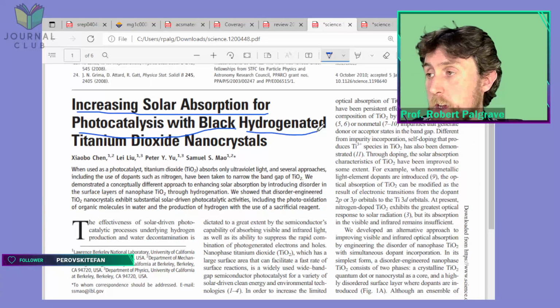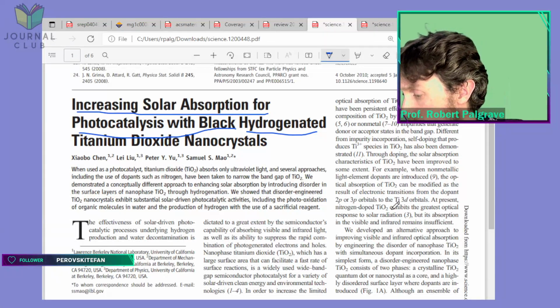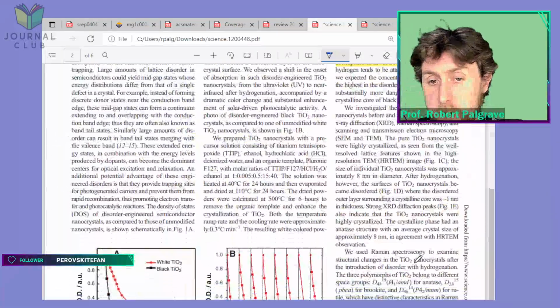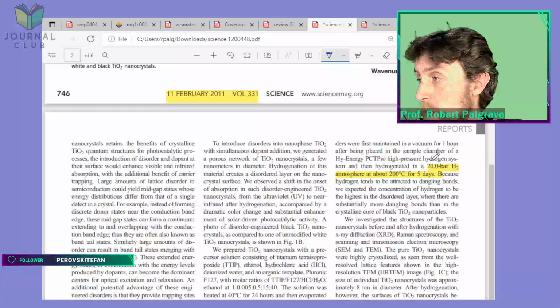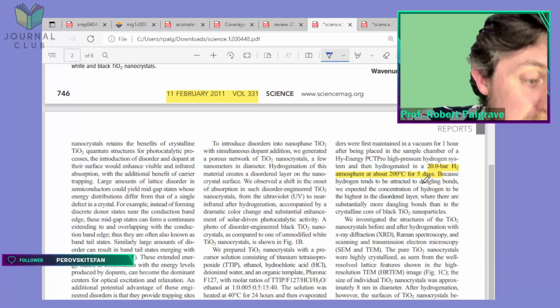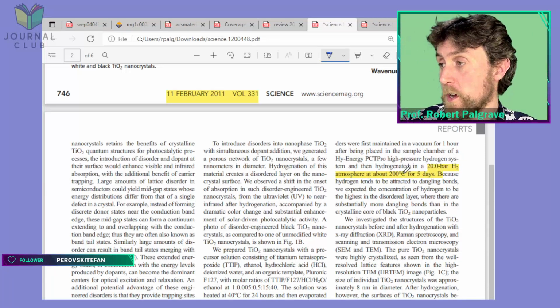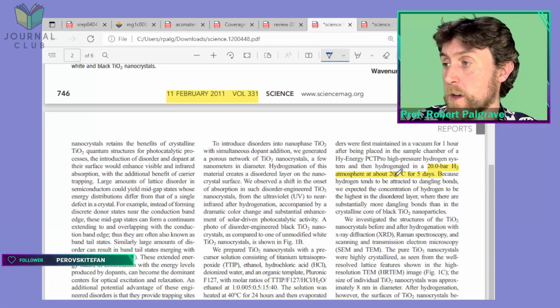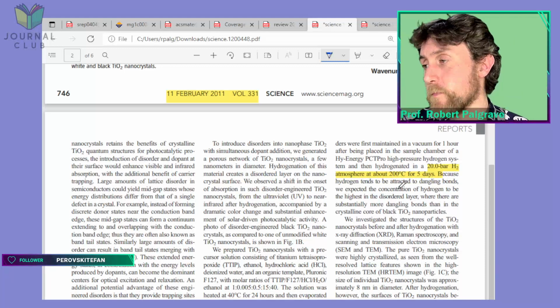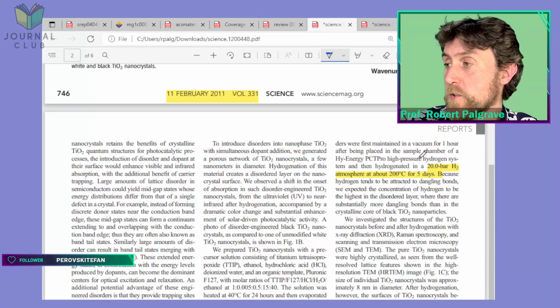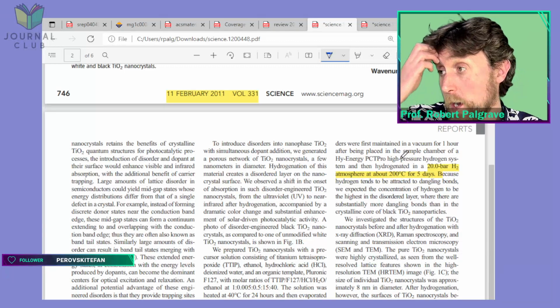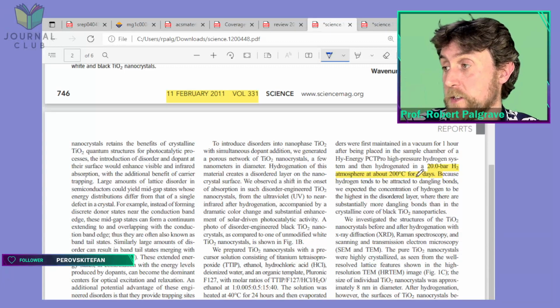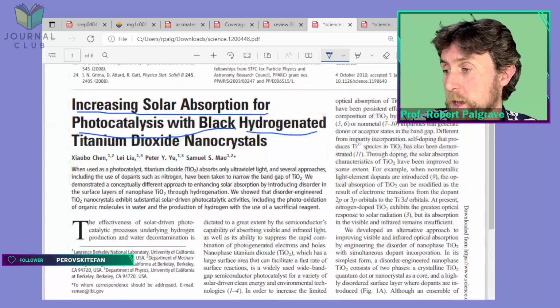Well, there's a clue in the title. They hydrogenated, so they reacted it with hydrogen, and in fact I can't remember where it is, I even highlighted it. The experimental method was quite extreme, so they used 20 atmospheric pressure, so 20 times atmospheric pressure of hydrogen at 200 degrees. They put their TiO2 powder in there and cooked it under huge pressure of hydrogen for 5 days at 200 degrees, and what they ended up with was this black material here.